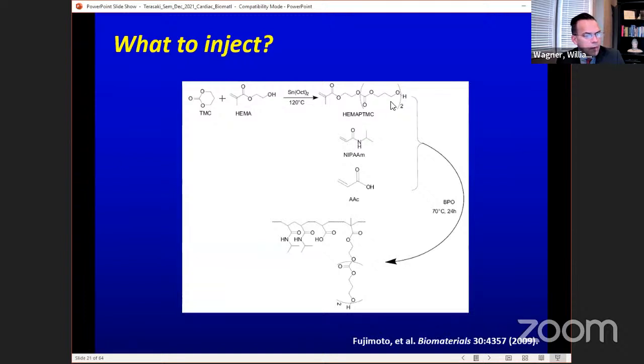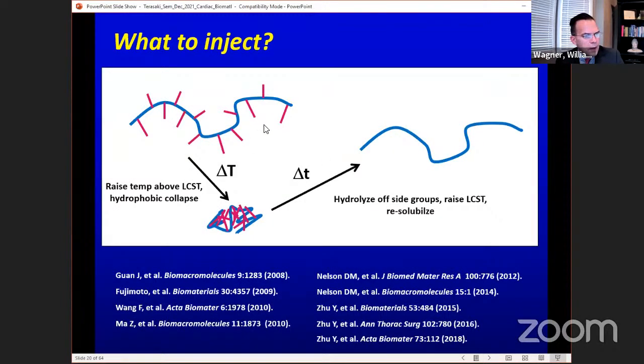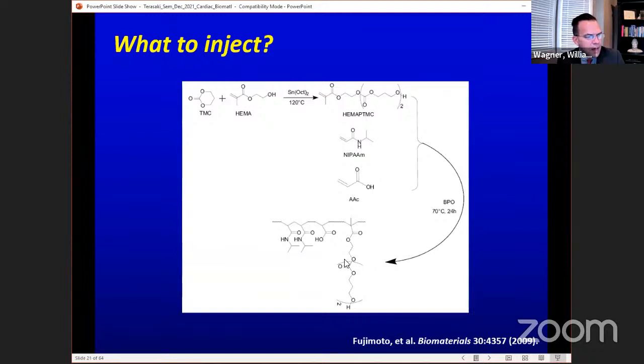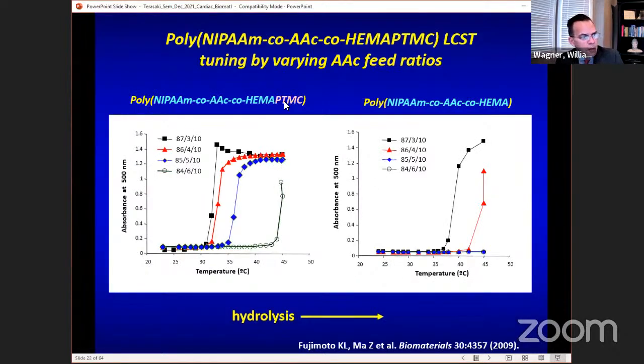Here's an example though. So we make this, the pink side branch is right here, and it's hanging down here. So trimethyl carbonate. So the carbonate is going to be the labile group. That's going to get cleaved. And then when that gets cleaved, these pink groups come off, and then this becomes soluble. Here's your N-isopropyl acrylamide, and this is just a hydrophilic acrylic acid that helps in the tuning of this. So the PTMC is that pink group. So here we have it on the polymer, and here we've cleaved it off. We've gone ahead chemically and cleaved it all off. And so you see, this is what it would be like when it's injected, using different molar ratios of this to make the addition polymer. And this would be after we cleaved it off.